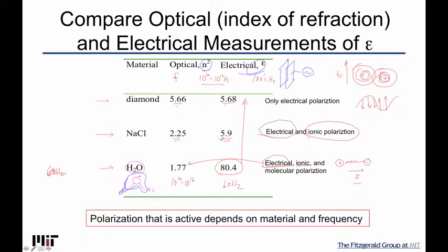This means that through these studies, it may be possible to separate out the electronic and ionic polarization with frequency. You can see that we did it here. At low frequency, I see both. At high frequency, I only have the electronic. That should allow me to extract what each atom is looking like from a polarization point of view. And it turns out, when I do that, a fundamental thing of an atomic polarizability, there's a volume associated with it. And that allows us to understand different size ions in different crystals.